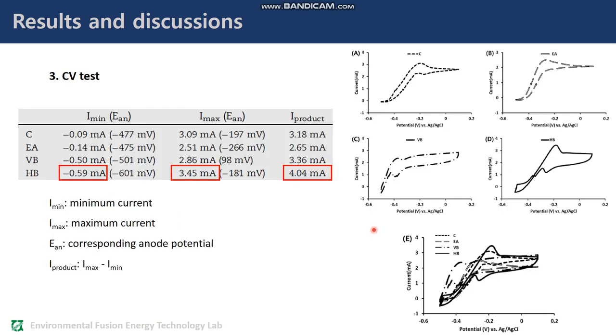Three, CV test. CV was measured to observe anode electrochemical reaction, excluding cathode effects. For each type, anode CVs were measured in 3 cycles, and last cycle data was used. Comparing the amount of current produced by each anode configuration, HB produced the best maximum current with 4.04 mA, followed by VB with 3.36 mA, C with 3.18 mA, and EA with 2.65 mA. The brush anodes produced 6 to 52% higher current than the cloth anodes.